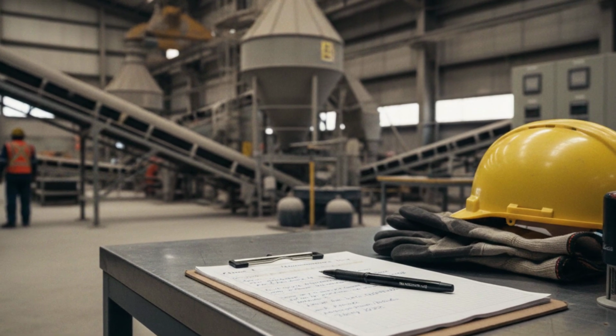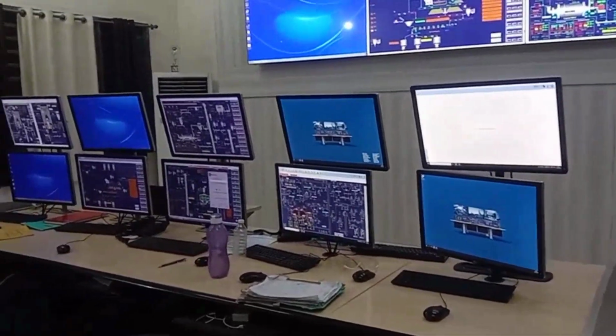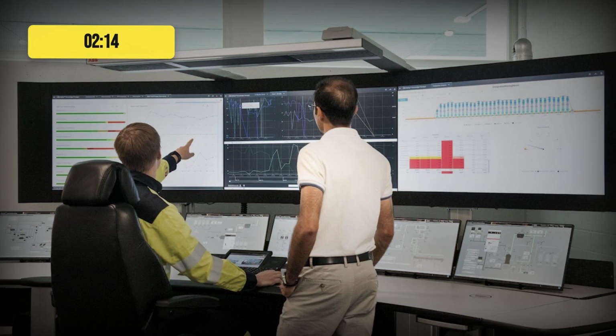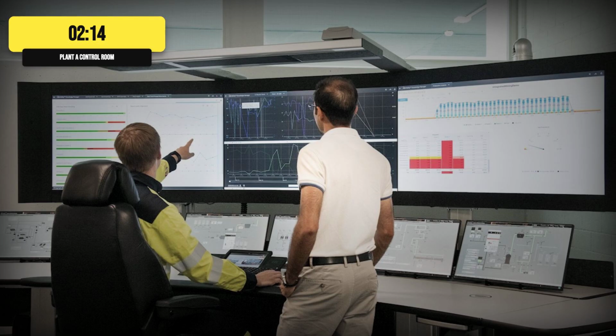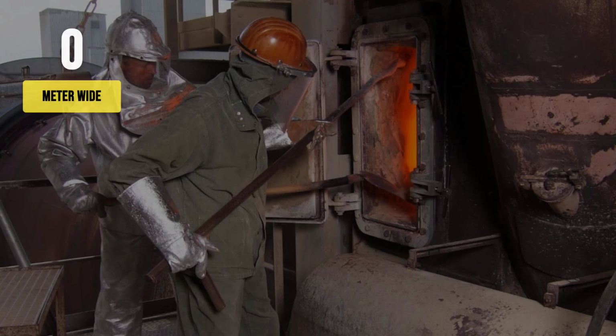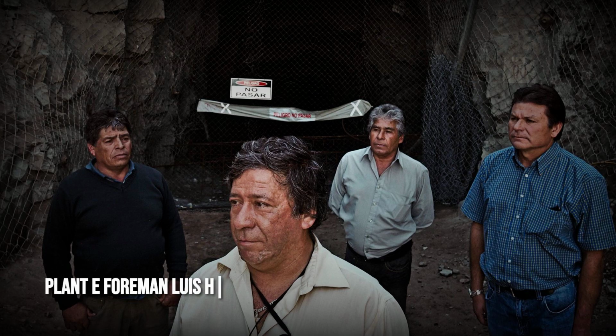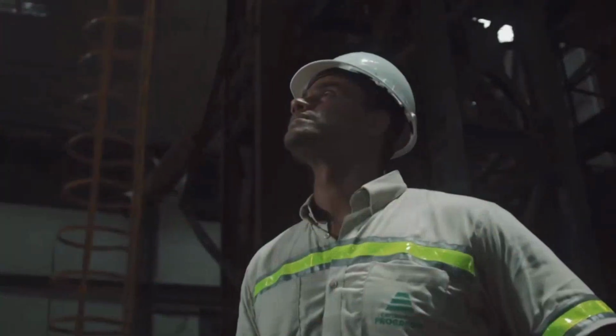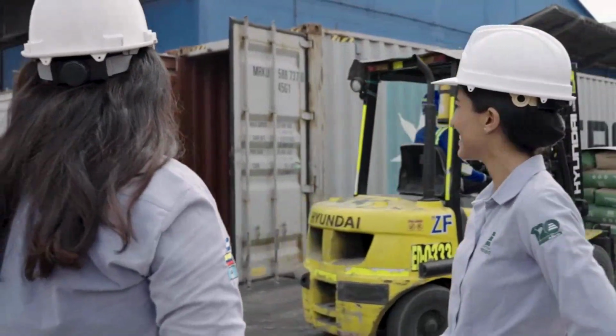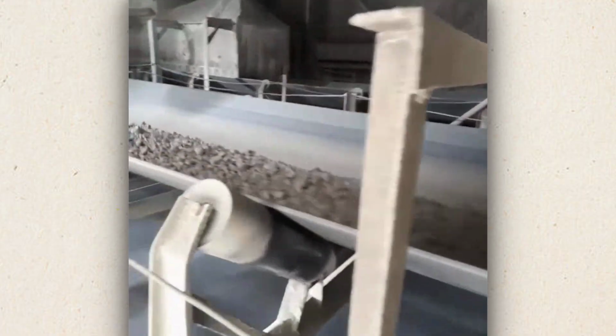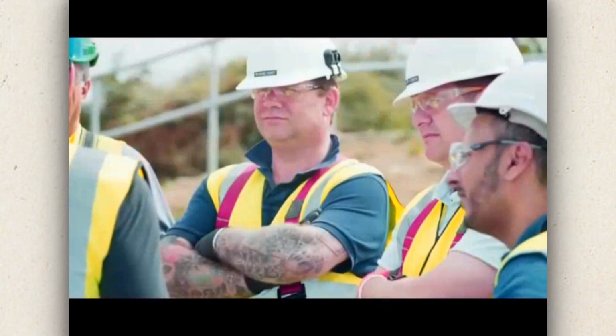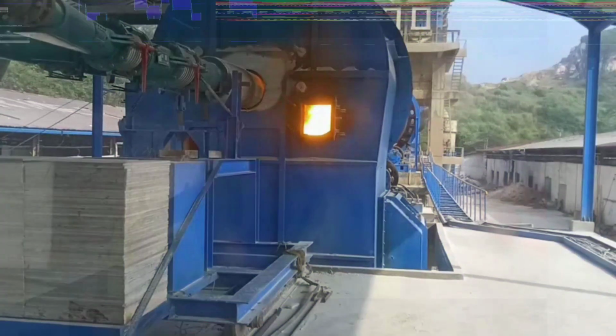The maintenance log from February 2022 captures the crisis in real time. At 2:14 in the morning, the control room logged a sudden drop in cooler draft. By 2:31 in the morning, the internal camera confirmed a snowman nearly 1 meter wide perched at the discharge. Plant A maintenance foreman Luis Herrera called in his team. Luis Herrera recalls that every minute counted and they had less than an hour before the line would grind to a halt. The response was fast and deliberate.